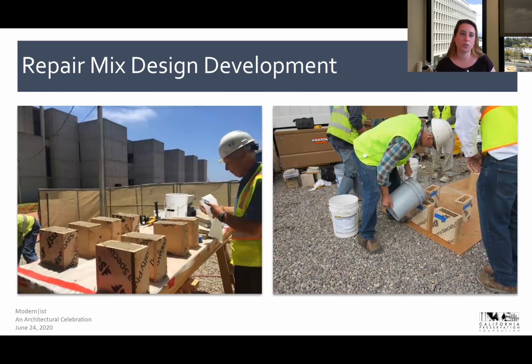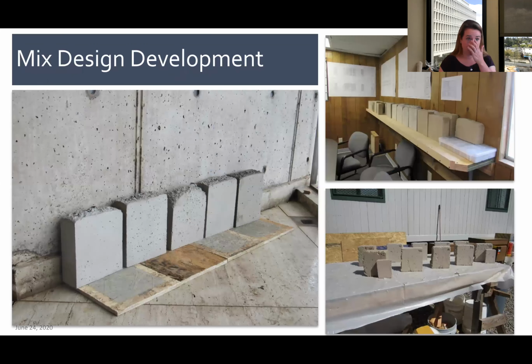And then we moved into the development of a repair mix design. Again, this was done off-site or off-building, and it was a long process. It definitely took a while for it to be completed. I think ultimately there were 45 to 50 trial mix designs developed that the contractor ended up building a shelf within their field office for all of these. But within these mix designs, we're looking not only at color, but can the contractor work with it? Is it constructible? And can we achieve the finish that we need, essentially getting those bug holes?